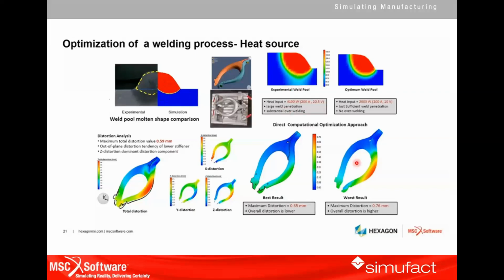Due to the overwelding, some areas gave higher distortion at the end due to large shrinkage effects which can happen after the welding process. But once we reduced the heat input, or the power, they were able to get sufficient penetration as compared to the experimental value shown here, as well as optimize the distortion. It came to around 0.35 from 0.75 mm. That is shown here in the best result.